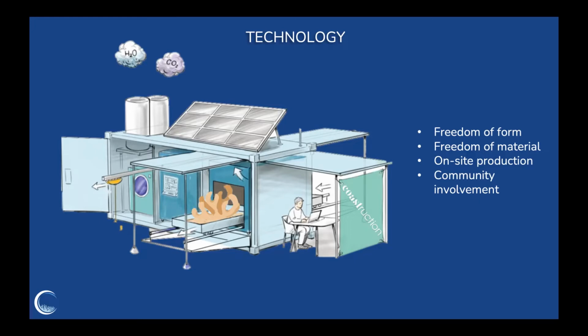And that is why a lot of times in extrusion printing, they add chemical additives to speed up this hardening process. Well, we say that there is already problems enough in the ocean, so we don't want to use chemical additives, and that's why we print with water or seawater. And another option is that we print with carbonated water to capture the CO2 in the cement. This is something we've done, and it works. And now the next step is to quantify how much CO2 we would actually capture.